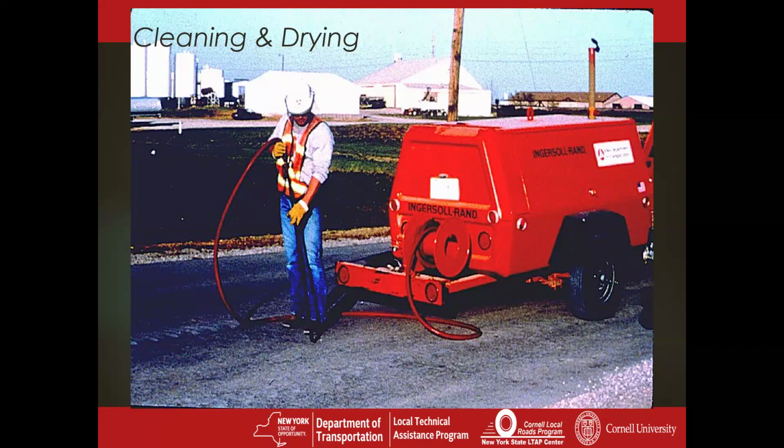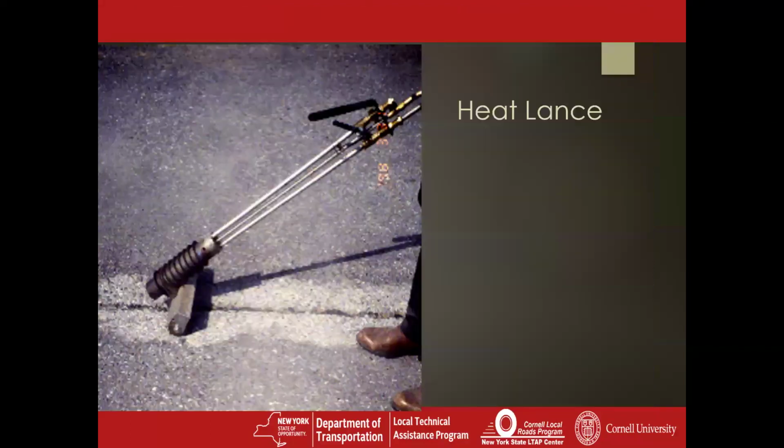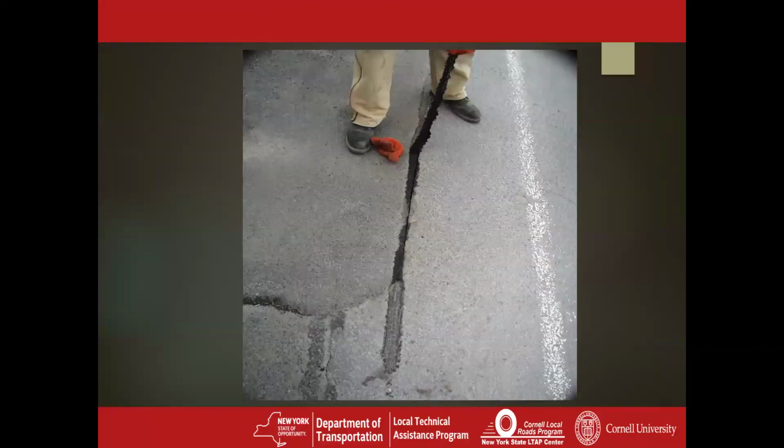However, it was pointed out by one of the other participants last year that particular IR rig has their oil water separator underneath the housing. So the main thing is you've got to have an oil water separator. You don't want to be blowing droplets of water and oil into your brand new cut crack.